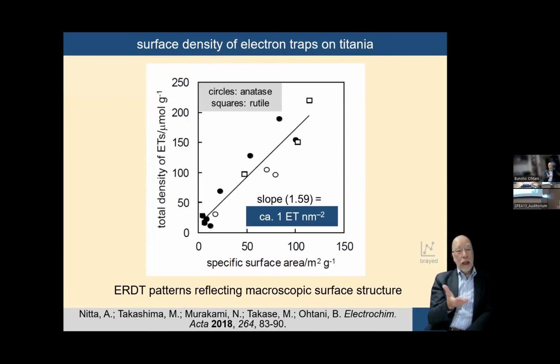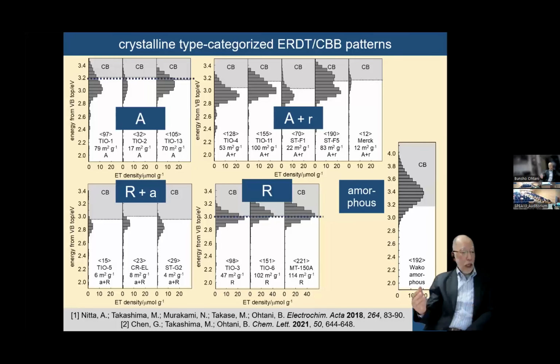An important point is that the total density of electron traps is almost proportional, not completely, to the specific surface area. This means that electron traps are located on the surface and are not something like point defects, but rather surface reconstruction structure. For example, in the anatase-only samples, left top, the CBB position is almost the same, so CBB position shows the bulk structure. For rutile, similar to anatase, the CBB position is almost the same, reflecting the bulk structure of rutile. But anatase-with-rutile samples show a bit different CBB position depending on the bulk structure.